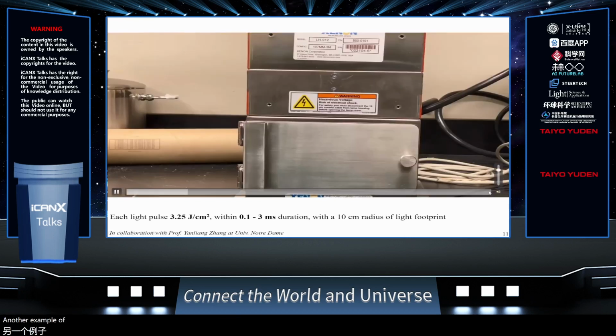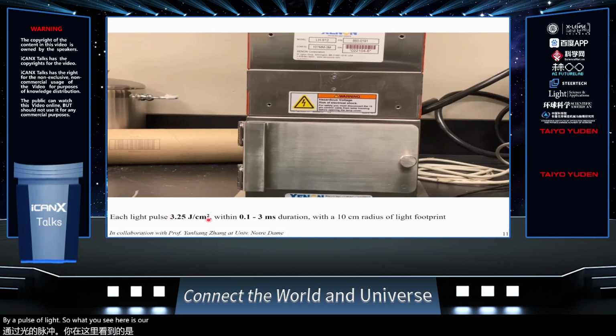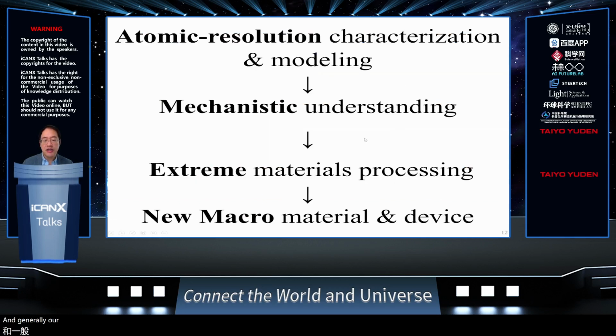Another example of this extreme processing is by a pulse of light. So what you see here is we can have a few joules per centimeter squared photon energy within a very short duration. This is in collaboration with Professor Yanliang Zhang at the University of Notre Dame to treat surfaces. And generally, our approach is we try to understand what happens at the atomic scale by doing characterizations such as transmission electron microscopy, as well as first principles modeling to try to get a grasp of the mechanism. And once we have the mechanism, we can go back and use active learning to tune the processing parameters, and the hope is to be able to rapidly process materials at the macro scale.